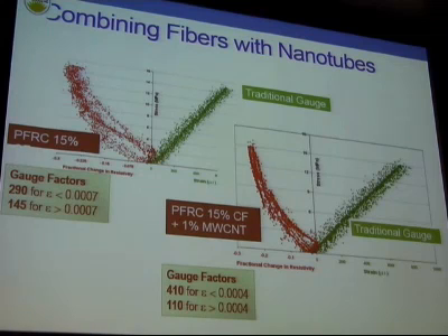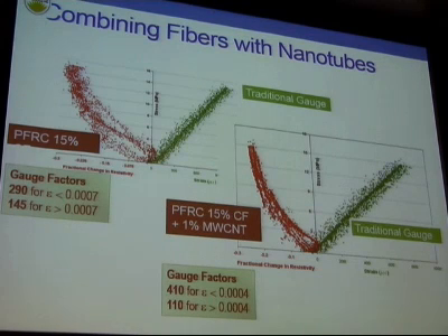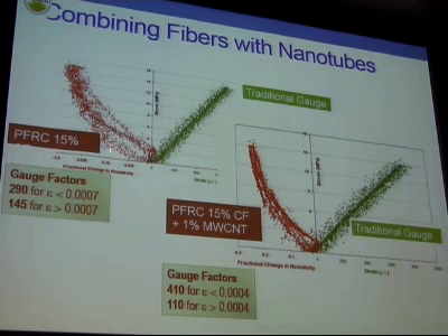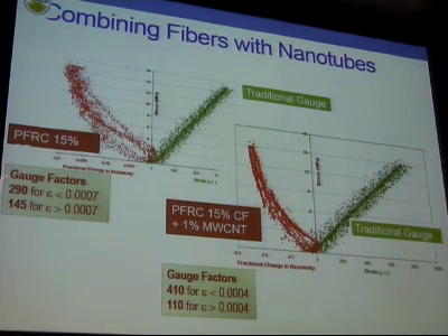And these are some of the calibration curves from the materials that we are developing with nanotubes. Here's your traditional sensor, very linear. Here is your PFRC sensor, piezoresistive FRC with 15% fiber: nonlinear response, very high gauge factors, which is in fact an order of magnitude greater than your traditional gauges or electrical gauges that we use. And here is the other material which has 1% multi-wall carbon nanotube. You can see that again the gauge factors are even higher, which means now you have a sensor which is extremely sensitive, and it can tell you very quickly what the stress level on the element is by simply hooking it up to an electrical inlet.